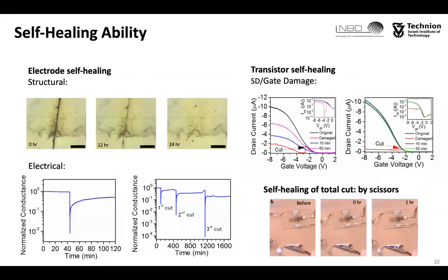The device, as you can see, behaves exactly as we predicted and wanted. If we scratch the device, then after 12 hours you can see that the scratch starts to disappear step by step. After 24 hours, the scratch closes autonomously, without any intervention, and heals 100%.